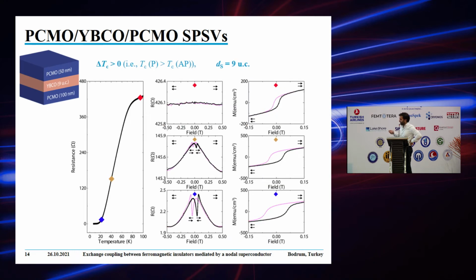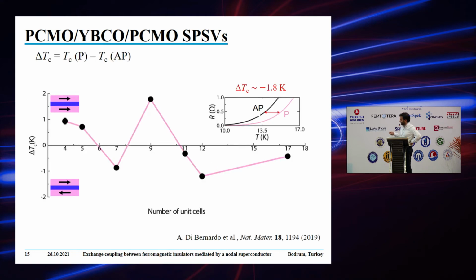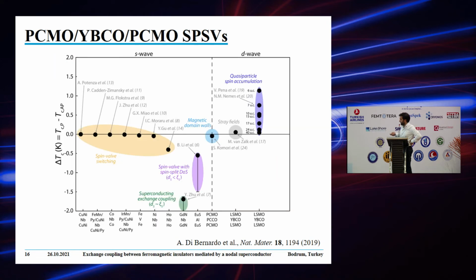Now, for a thinner YBCO, in this case we observed that the parallel state is the state of low resistance, which means high TC, and when this is the case, there is no increase in these antiparallel regions of the MH loop. So this is again also strong evidence of the fact that the parallel state is the state with high TC. So low resistance means high TC. If you plot this as a function of the thickness of the YBCO, you see that for large thicknesses, mostly the spin valve prefers this antiparallel state. So delta TC, that is defined like this, is negative. And for low thicknesses, instead, it favors the parallel state.